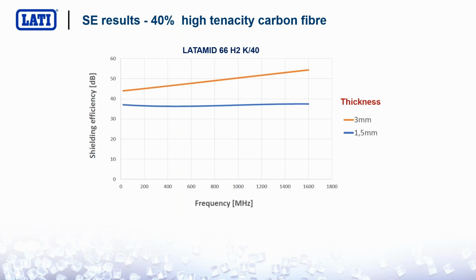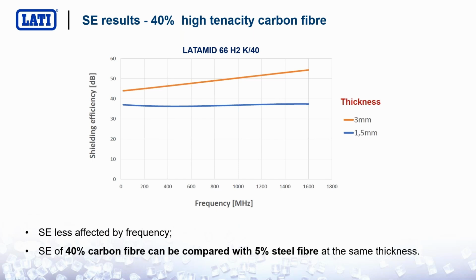The second set of results is describing the behavior of carbon fibers. We wanted to test 40% carbon fiber, high tenacity carbon fiber, and the results are very interesting. What can be seen here is that there is also in this case a slight improvement by increasing thickness, but it is not as evident as with steel. And what is more important, these curves are more or less linear with frequency. This is also very interesting because this means that if we use carbon fiber for shielding purposes, the shielding efficiency will be less affected by frequency, and 40% carbon fiber can provide the same performance as 5% steel as an attenuation value.